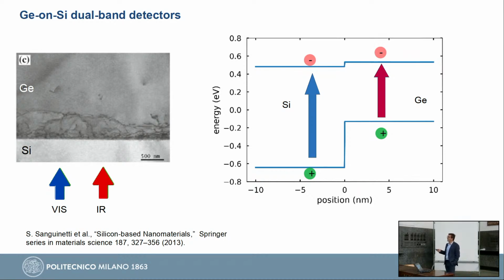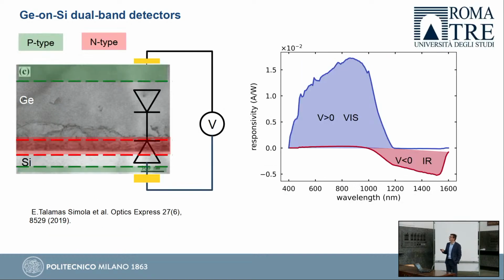To actually get some photocurrent, some signal out of this device, you need some additional steps. You need to make a p-n junction here and a p-n junction here. In this way, you essentially form a device with two diodes, one opposite to the other, in a back-to-back configuration. This means that if you apply, for example, a positive bias to the system, you will have a photocurrent coming only from silicon. The photocurrent will look like this, going from 400 nanometers to 1200 nanometers, which is basically the limit set by the energy gap of silicon. If you instead use a negative bias, you will have light absorbed in the germanium part, and so you will only see the infrared part, with a small overlap. This means that with a single pixel, like this structure here, you can actually take two images.